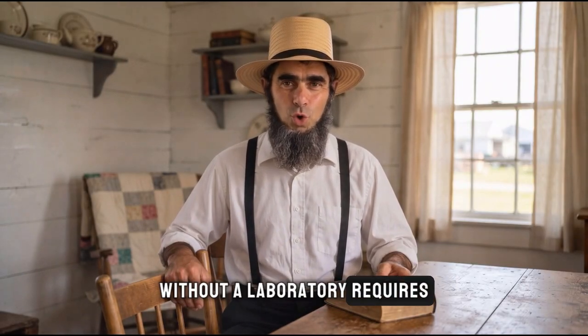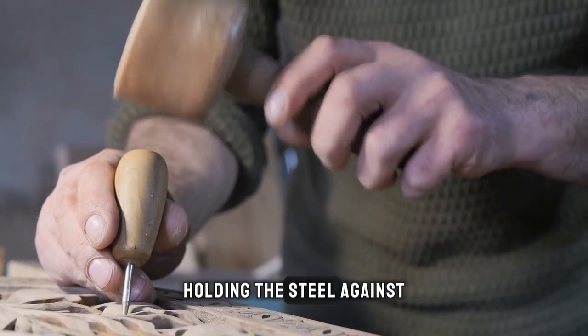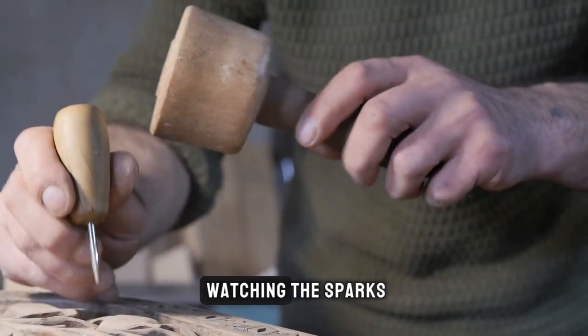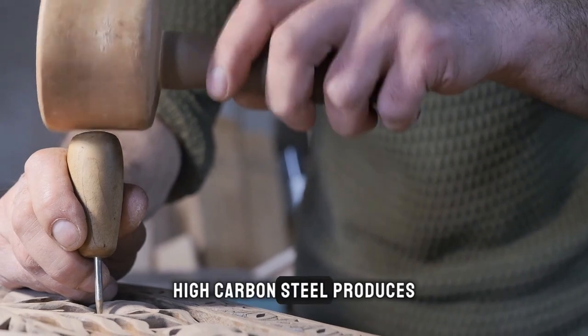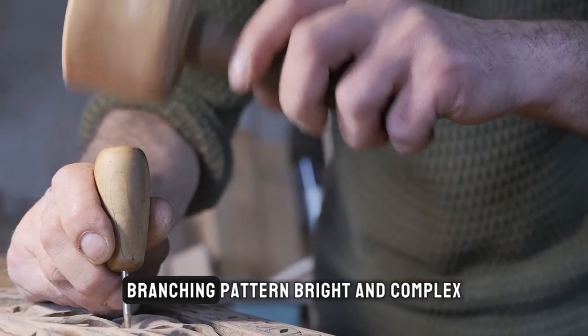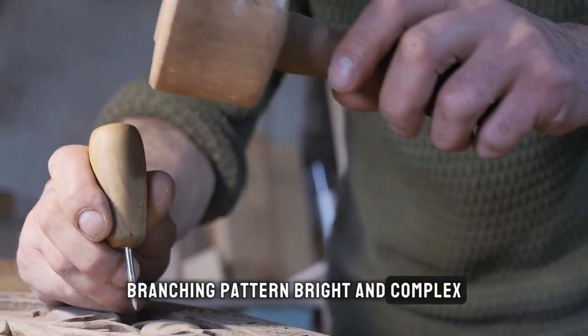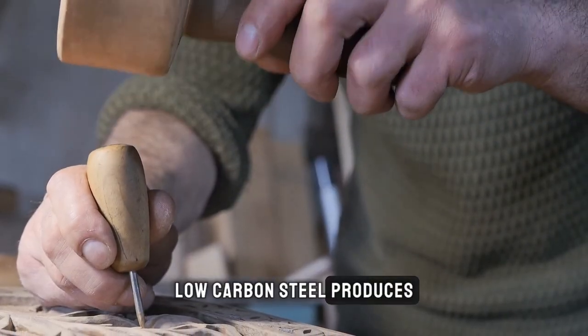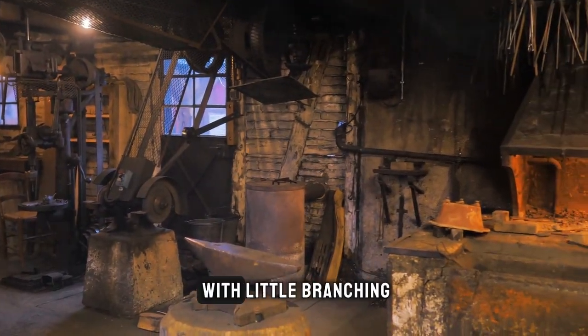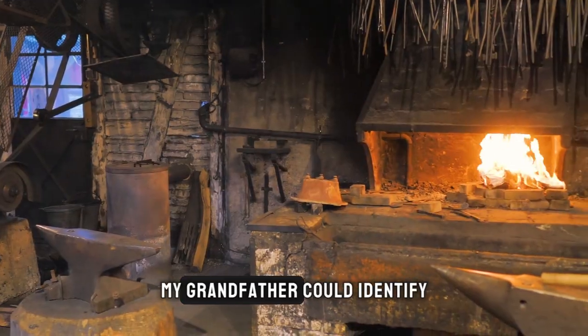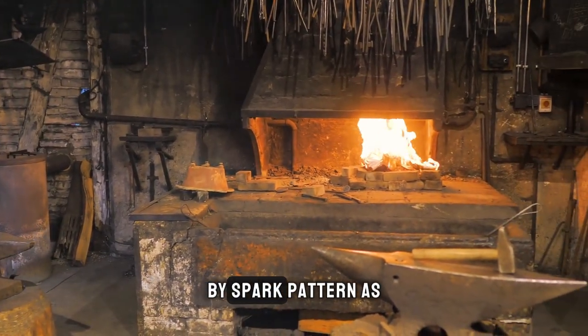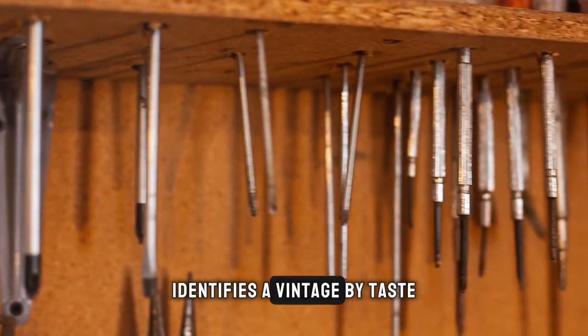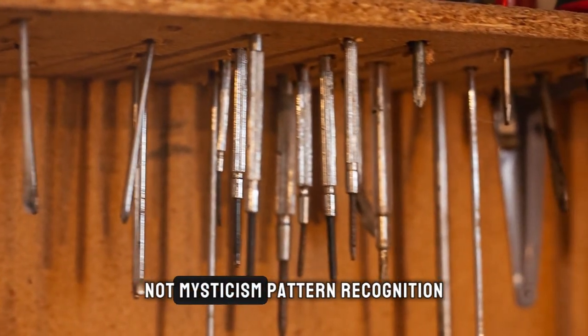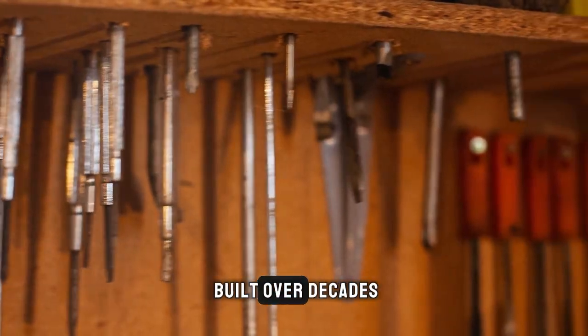Identifying high-carbon steel without a laboratory requires a spark test, holding the steel against a bench grinder and watching the sparks. High-carbon steel produces a burst, branching pattern, bright and complex. Low-carbon steel produces a long, simple trail with little branching. My grandfather could identify steel grade by spark pattern as reliably as a sommelier identifies a vintage by taste. Not mysticism, pattern recognition built over decades.